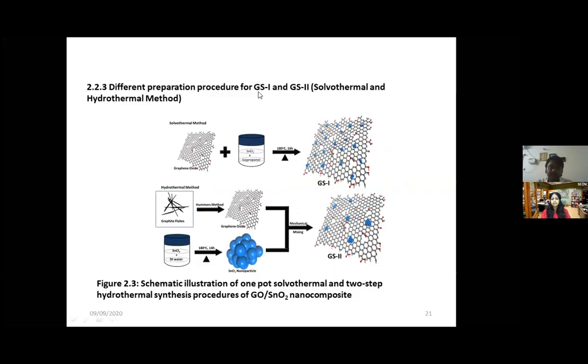So this slide discusses the same sensor material, graphene oxide and tin dioxide, made by two different synthesis procedures. The first is the one-pot solvothermal method, which we discussed in the previous slide. That will be represented as GS1 from this slide. And the second one is the two-pot hydrothermal method. This is a simple illustration of the work we discussed in the previous slide, one-pot solvothermal. Here what we did is the two-pot hydrothermal method. First we prepared graphene oxide using the Hummers method, and the second step is done with the help of the hydrothermal method. The name indicates that we use DI water here. Same tin oxide precursor, maintained in a muffle furnace, transferred to an autoclave, maintained at this temperature and duration, cooled down to room temperature, and transferred to a centrifuge tube. All the same procedure.